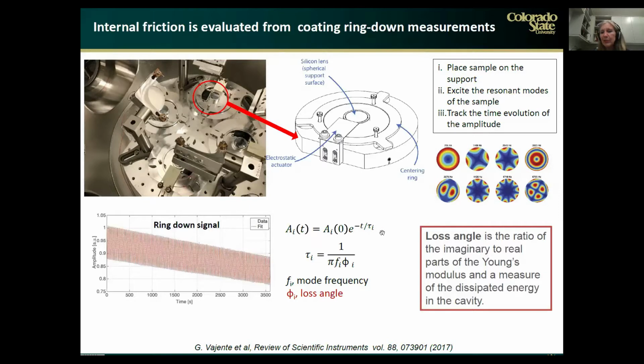This is the expression of the amplitude of the different modes of oscillation, and what we measure is the decay time that is related to the loss angle. The loss angle is the ratio of the imaginary to real parts of the Young modulus, and is a measure of the dissipated energy in the cavity.